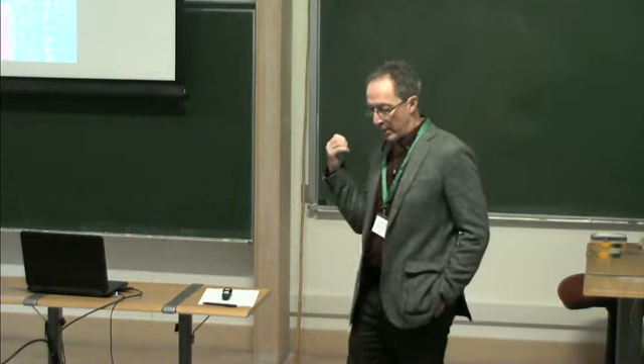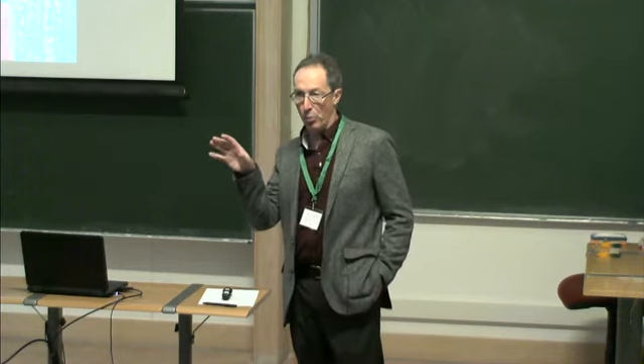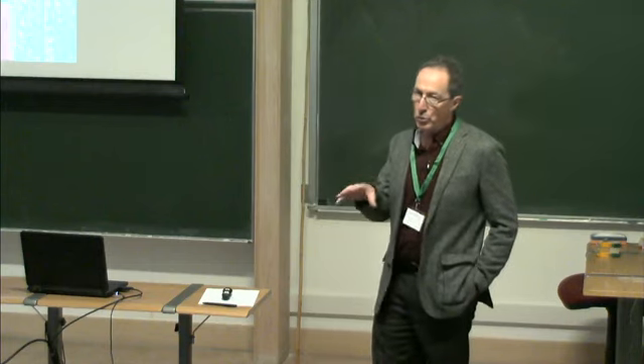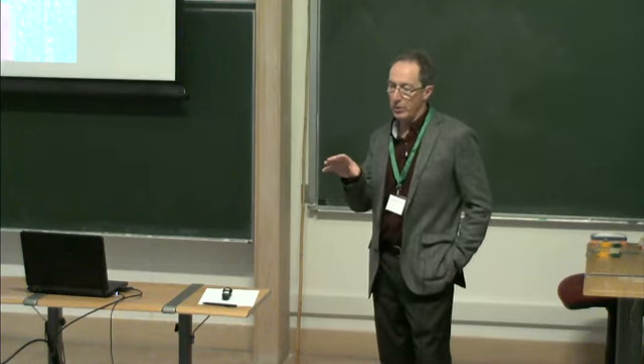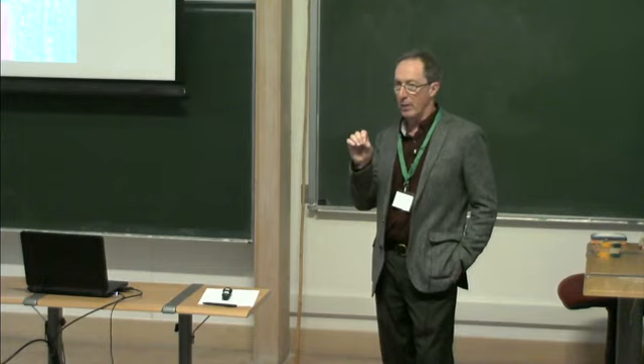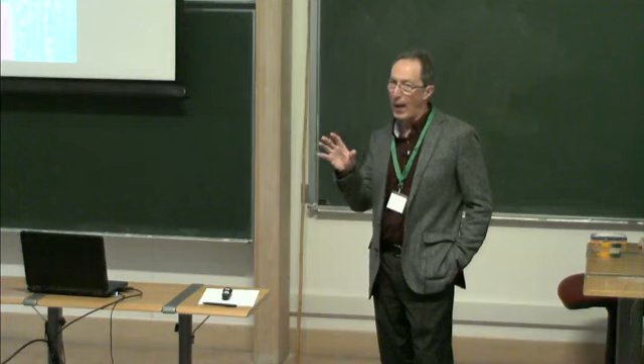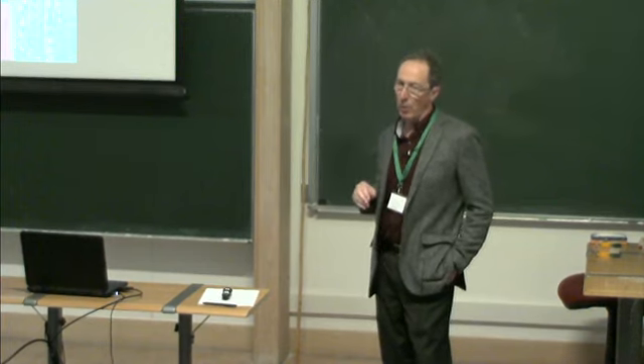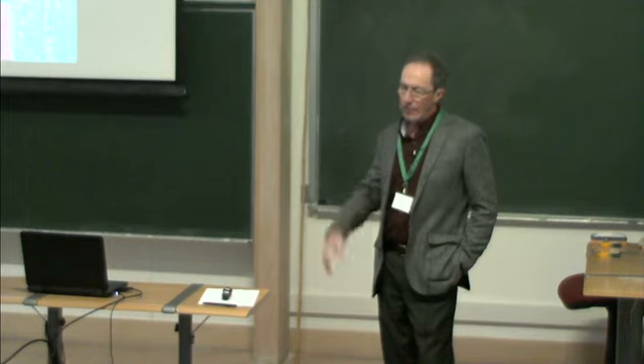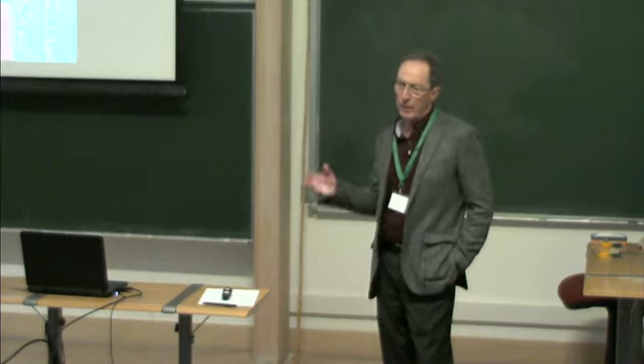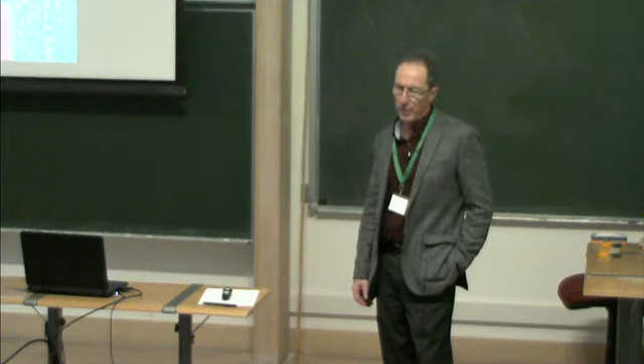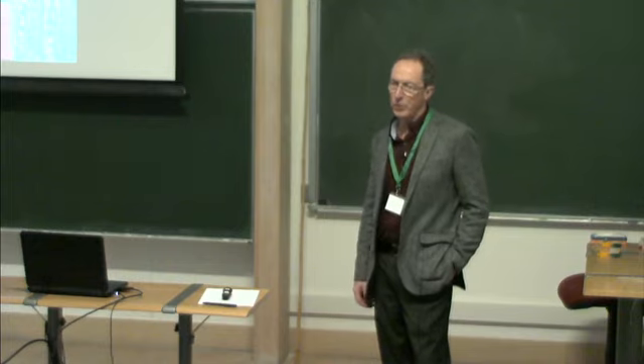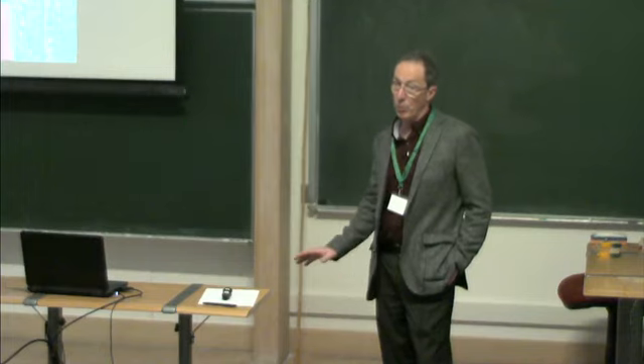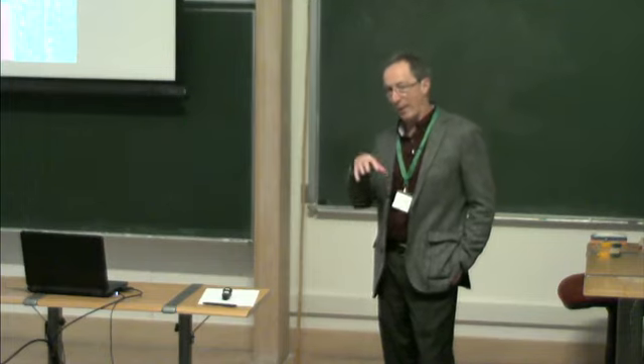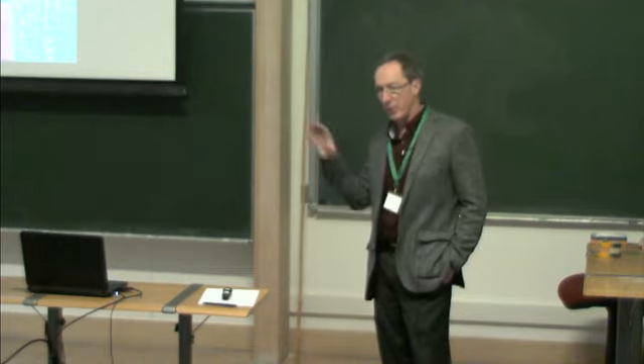I didn't get into that level of detail, but with that plot with all the Barnes, Tabor, and Walker data, I deduce from that analysis that activation energy is somewhat lower. It might be 0.25, so 0.2 of an eV lower in freshwater ice. But the hope is that either Ian Baker and I at Dartmouth get some funding on this line, or I can con the Australians into running these experiments in shear, which I hope would work out. So we would actually get those hard numbers for freshwater ice to validate that.